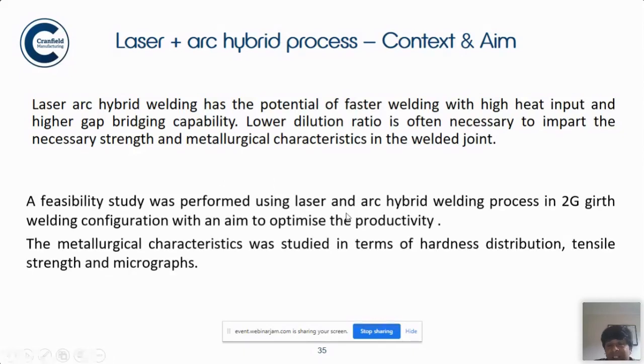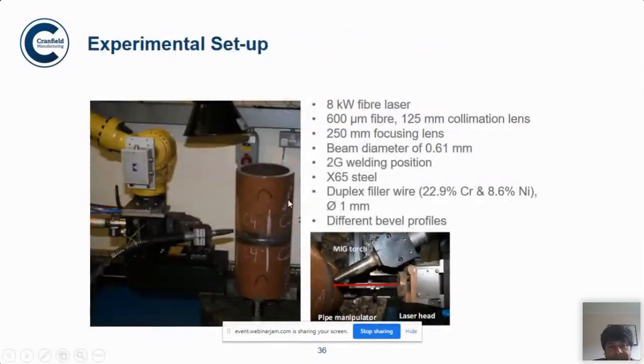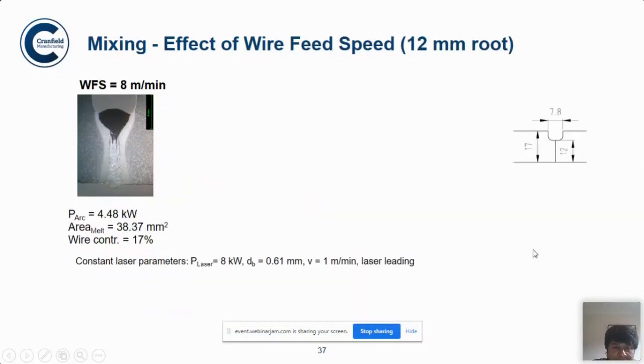So we have done a feasibility study using laser and laser plus arc hybrid process in 2G welding configuration with an aim to optimize the productivity. So you will see in the next slide. So this is the setup. This is the pipeline that we are welding. This is 2G configuration. Basically the pipe is vertical and the welding torch is coming horizontally. And some details are given here, which is not very important at this stage. The most important thing is this one.